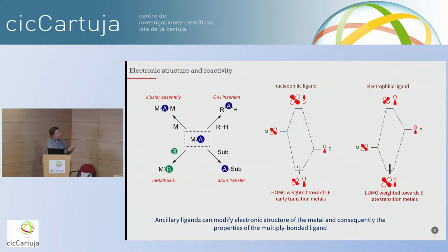Another thing I should point out is that it's possible to change the reactivity of this ligand by playing with the other ligands on the metal. So for example, if your metal d orbitals are higher in energy than the frontier orbitals of the multiply bonded ligand, then the HOMO is going to be weighted towards this element. That means this will be a nucleophilic ligand.